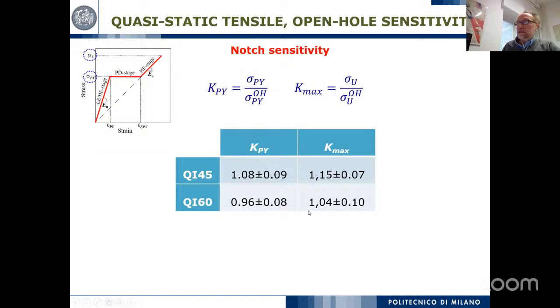And then you can see that the notch sensitivity is quite good. We are close to 1. Namely, we have the same response as the unnotched material, and this is reasonable, and this is due to this distribution of damage in the more stressed part of the material that allows you to exploit this range of pseudo-ductility, and then to continue increasing the load also at higher strain level.